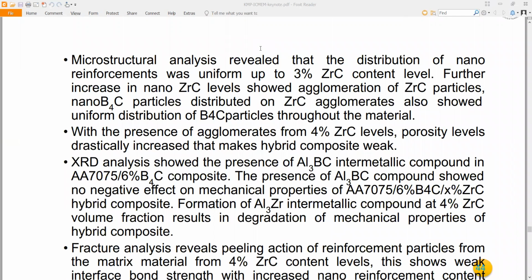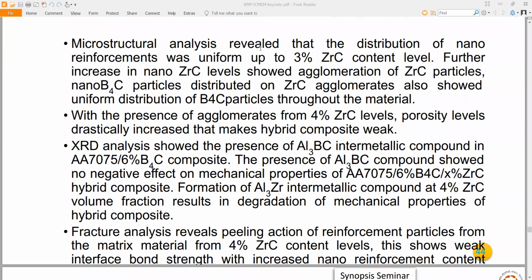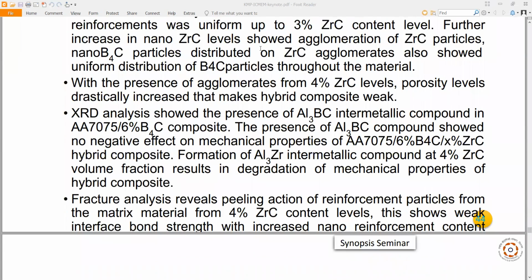Then next is microstructural analysis, which revealed that the distribution of nano reinforcement was uniform up to 3% ZrC content level, and a further increase in nano ZrC level showed agglomerations of ZrC particles. Nano B4C particles distributed on ZrC agglomerates also showed uniform distribution of B4C particles throughout the material. Then, with the presence of agglomerates from 4% ZrC level, porosity level drastically increased, which makes the hybrid composite weak.